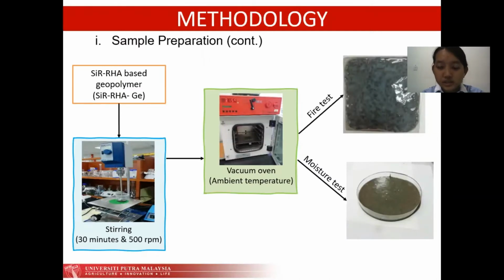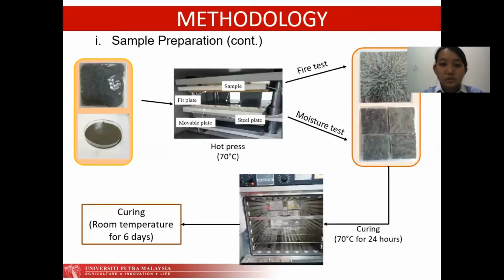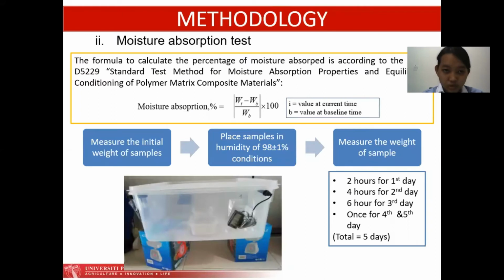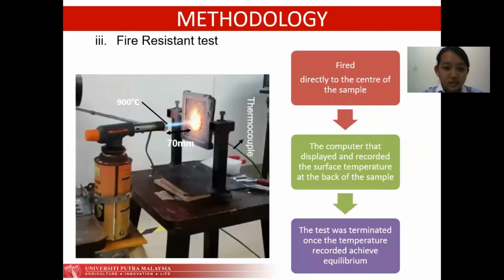Actually, in this study, two patterns of sample will be prepared, one for the fire test and one for the moisture test. For the fire test, the mixture was coated onto the surface of a mild steel plate and evenly sprayed. But for the moisture test, the mixture is poured directly onto the packing paper without the mild steel plate. After the pressing process, the desired thickness of the sample for the fire test is about 1 mm, but for the moisture test, the thickness is about 3 mm. So this is the procedure for the moisture absorption test, and this is the procedure for the fire resistant test.